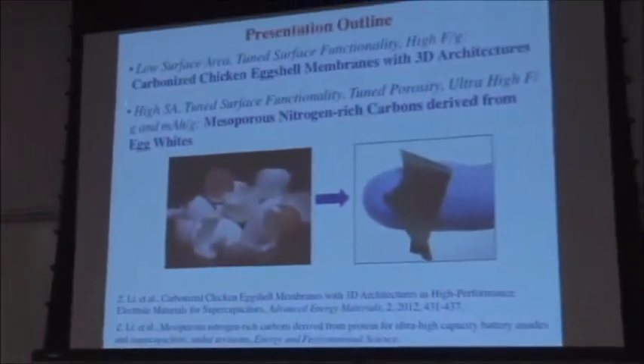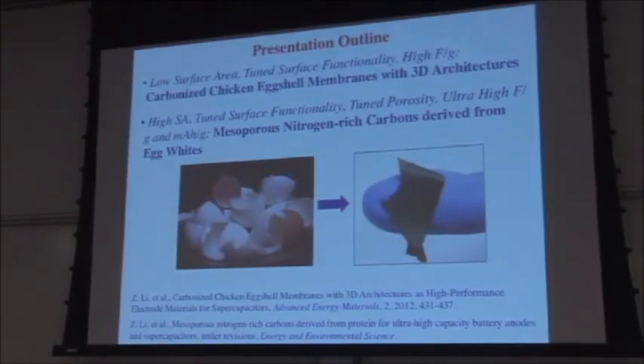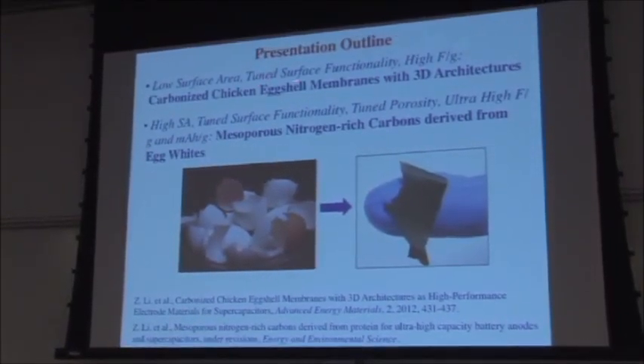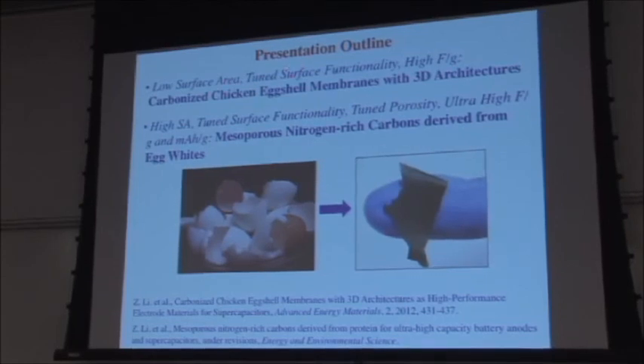So what if we could take carbons and run a combination of electrical double layer and Faradaic reactions in an aqueous system and achieve on par energy densities? And what I'm going to talk about is really 2 topics. The first part of the presentation, which is what was in the abstract, is a very low surface area material with very high nitrogen content and tuned surface functionality. And with that, you get quite high farads per gram. And this is the carbonized chicken eggshell membrane with 3D architectures.